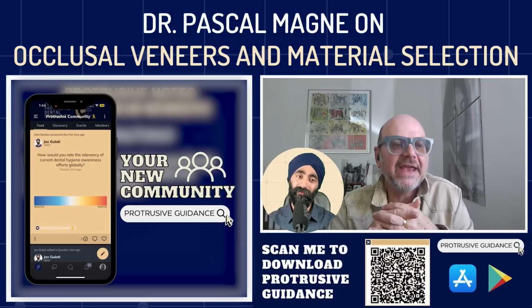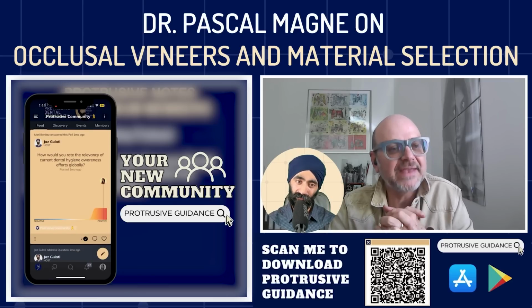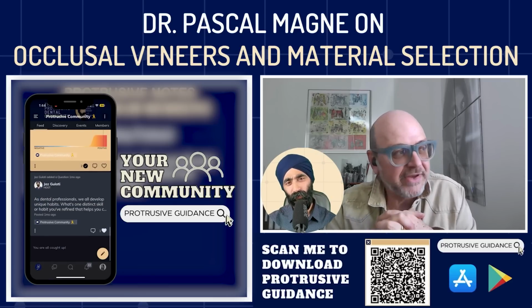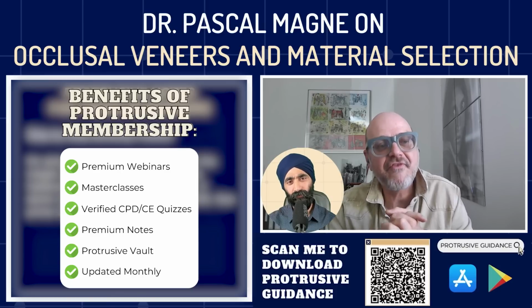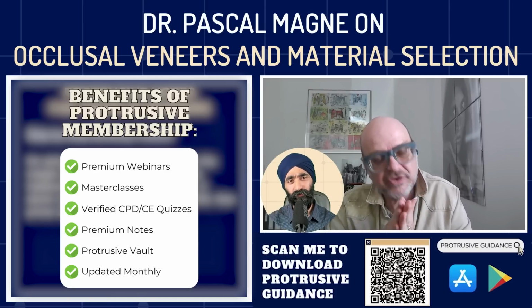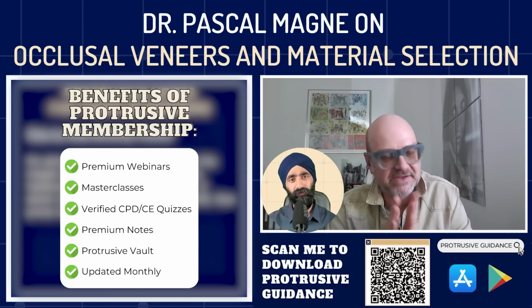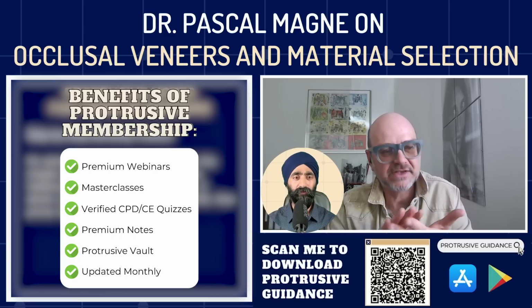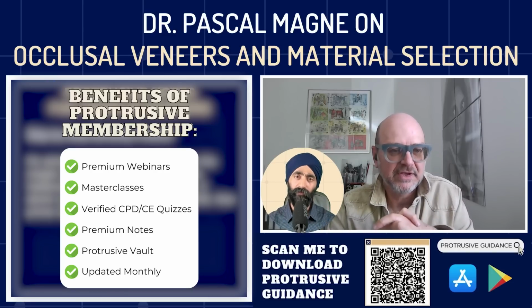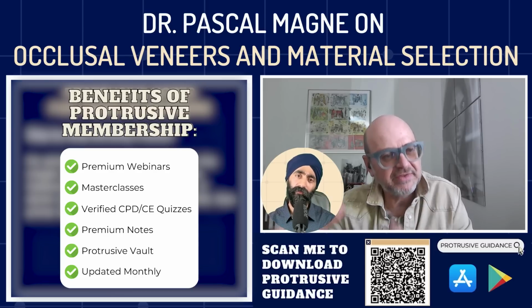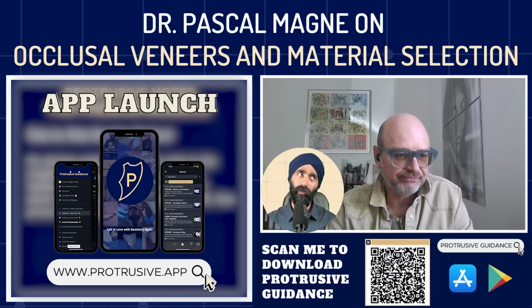So the heat drying of the silane is very important. And then when you use preheated restorative material, it's very important to wet the restoration with adhesive resin. For my part, I use the second bottle of Optibond FL. So the tooth is air abraded and etched, resin coated with Optibond FL bottle number 2.